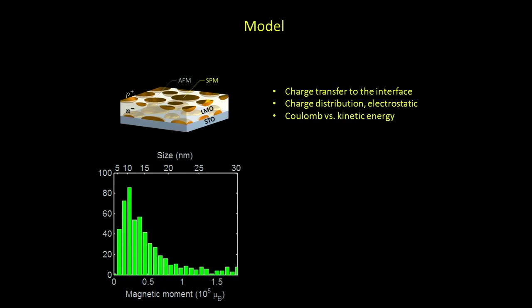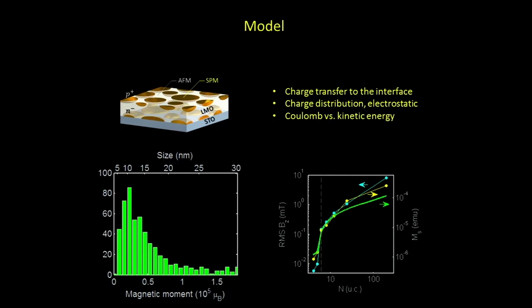We can calculate the histogram of sizes measured experimentally and the model gives about 10 nanometers, which corresponds to the peak of our distribution. Using this model, the calculated saturation magnetization follows the global measurement quite well. To finish: if this is a super-paramagnet, does it have thermally-activated flips even at 4.2 kelvin? Are there particles that flip with time?